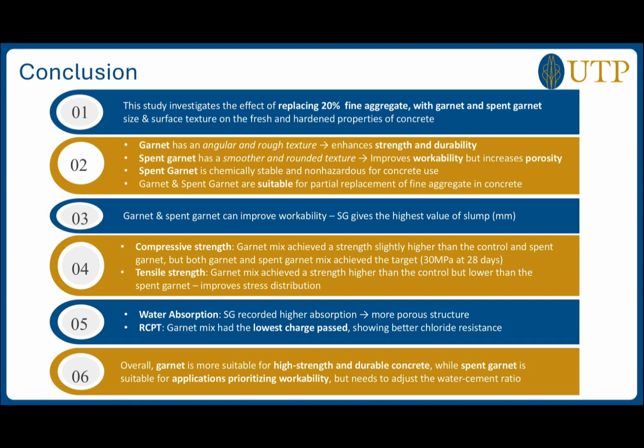So in conclusion, this study investigates the effect of replacing 20% of fine aggregate with garnet and spent garnet, size and surface texture, on the fresh and hardened properties of concrete. To fulfill objective number 1, physical properties have shown that garnet has an angular and rough texture, which can enhance strength and durability, and the spent garnet has a smoother and rounded texture, which can improve workability but increase porosity. And chemically, spent garnet is stable and non-hazardous for concrete use. Therefore, garnet and spent garnet are suitable for partial replacement of fine aggregate in concrete.